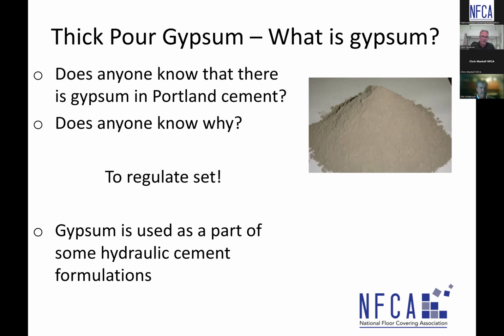You might have a Portland cement material or calcium aluminate cement material as the main binder. And if you look at an SDS, you may see a small amount of calcium sulfate in there. It's not necessarily a filler, but it's a part of the chemistry of the cement. And that's where the R&D chemists come into play, taking different types of cement and making products. So just because you see calcium sulfate on an SDS doesn't necessarily mean there's something negative about that product.